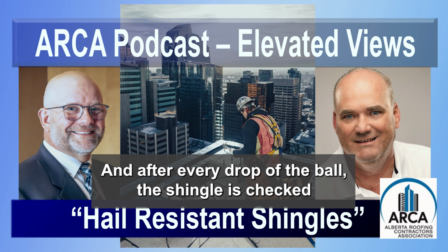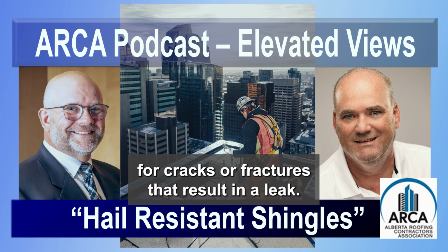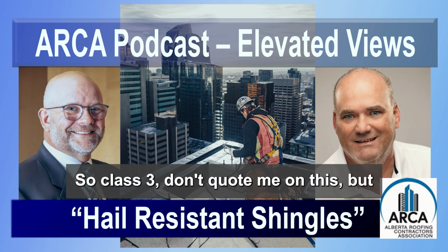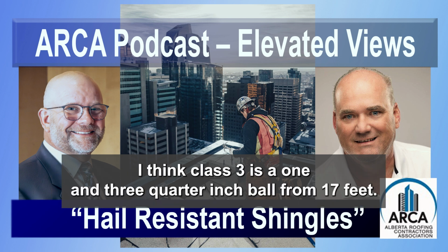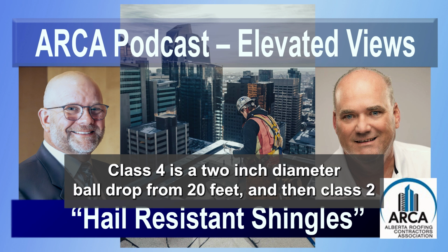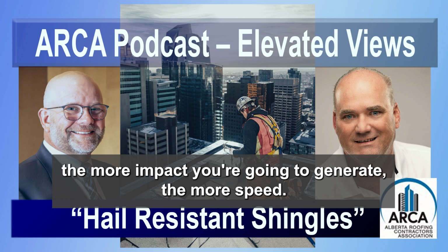After every drop of the ball, the shingle is checked for a crack or fracture that could result in a leak. So they're checking the back side of the shingle for cracks or fractures that result in a leak. Class 3, don't quote me on this, I think is a 1 3/4 inch ball from 17 feet. Class 4 is a 2-inch diameter ball dropped from 20 feet. And then Class 2 and Class 1 would be a smaller diameter ball bearing dropped from a lower distance. The higher you drop the ball from, the more impact you're going to generate, the more speed.